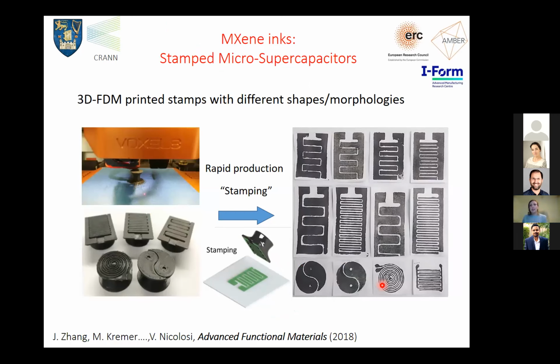And that allowed us to really explore applications that we had in mind, but we couldn't yet pursue because we always had been working with tricky, non-volatile solvents that were compatible with other classes of 2D systems. So it was always tricky. For example, in this case, we used a very simple methodology that used a 3D fused deposition printer to make stamps. And with this simple 3D printing, you can do stamps with any sort of geometry that you want. Of course, for supercapacitors, we love interdigitated geometries because they give us a lot of surface.